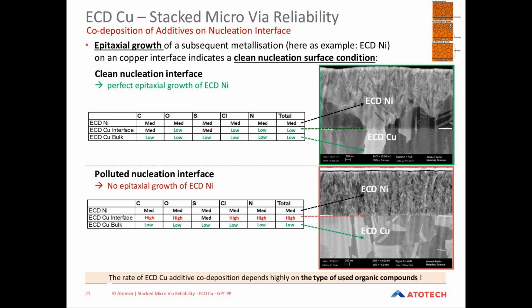Of course, here we talk about metals which have the same atomic lattice and metals which have a similar atomic diameter. Only then can you expect this epitaxial growth. But this would be the same for copper on copper, of course. Here we have the same metals. And if you see this epitaxial growth between both layers, you can expect that the interface was really clean and no strong adsorption of any kind of chemicals has disturbed the growth of the next metal layer on this interface.